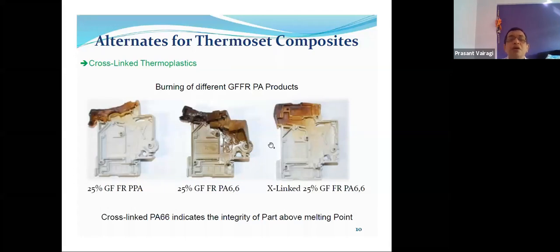Now, on the left side, there is a hot pin penetration test which we carry out. What we typically do is increase the temperature 90 degrees above the former melting point. So if nylon 66 has 260, 260 plus 90 is 350 degrees centigrade, we actually apply that temperature and see the pin has gone through and through. And you can see even the glow wire has completely squeezed out the material, because it is much more than the melting point. We do it within a fraction of a second; it doesn't have to be applied for much time.